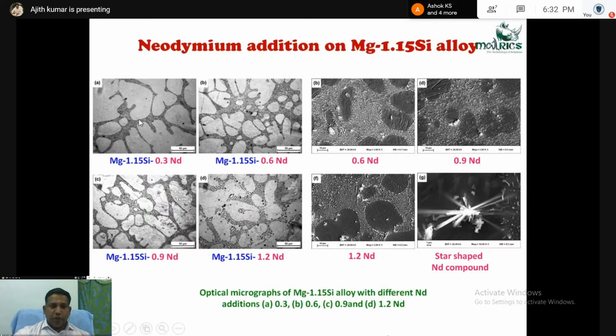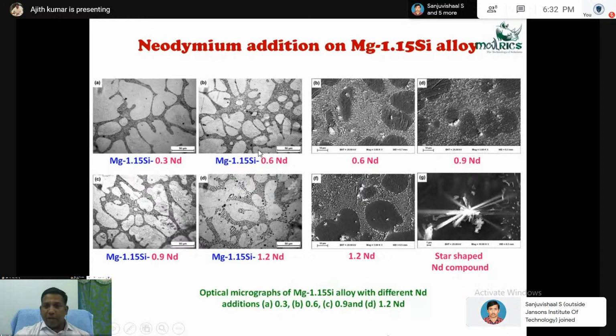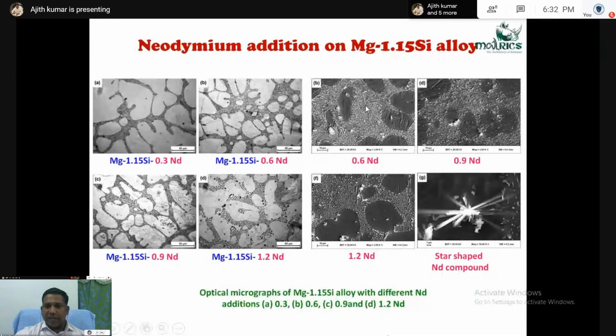With the addition of neodymium, you can see the coarse lamellar structure changes to a discontinuous lamellar structure in 0.3 Nd, 0.6 Nd. So with the different additions, you can see that variation in microstructure. In the high magnification views, if you see the lamellar eutectic structure, now the lamellar spacing is very less, and when you go to 0.9% Nd addition, there is no lamellar or line kind of structure. All the structures look like particle kind of structure. When it reached 1.2% Nd addition, we got some star kind of compound in the matrix or in the interdendritic region. That we analyzed using SEM.